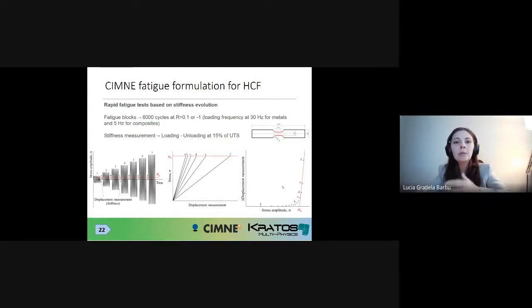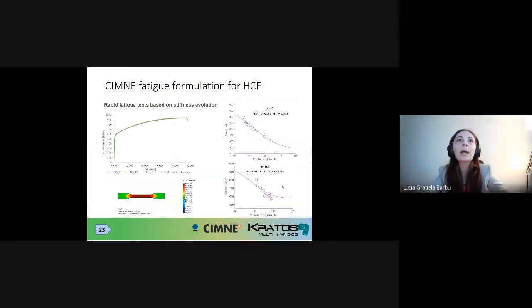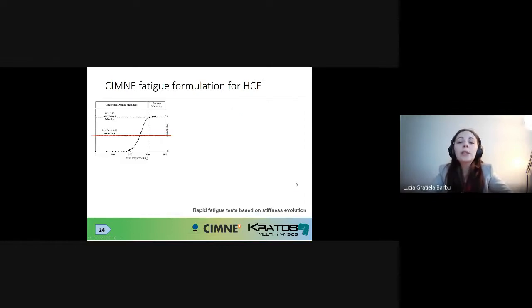And for us, it was interesting when they developed this experimental technique to see if our model, our formulation for high cycle fatigue, was capable of giving accurate results for this type of test also. And we began to do a calibration. It's specific for a TWIP steel. We began, as you do in a numerical simulation, calibrating the static parameters from the engineering stress strain curve. You can see here the experimental curve, and it's a very good adjustment with the numerical curve that we obtained when we calibrated our model parameters. Then we also calibrated our fatigue parameters for the minus one and for the 0.1 curves. And then we proceeded to evaluate if we obtain the same behavior after doing this rapid loading history with the blocks of cyclic load.